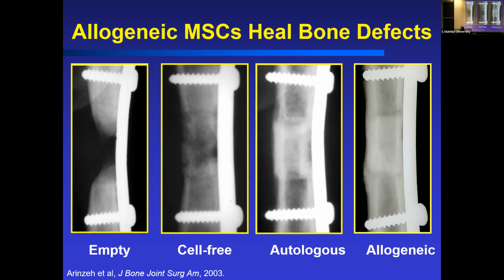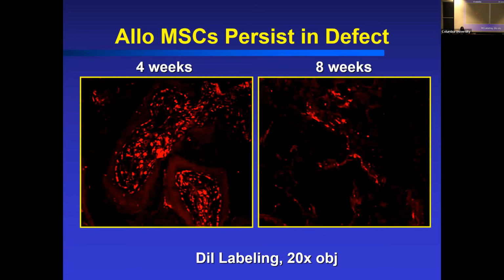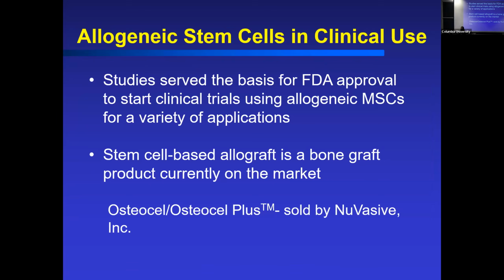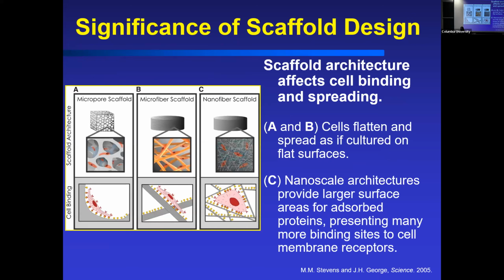So shown here are x-rays. Again, if you leave the bone untreated, you're left with this huge defect, right? Empty defect. But if you treat it with that combination of cells, you get this bridging of the defect. And so you follow that with a number of different outcomes of histology and we had to look for whether the cells were present. And so we were able to show that those cells were present in those tissues, building the bone tissue along with integrated with the scaffold over time. So this really served the basis then for FDA approval for the use of these donor cells for a number of clinical trials. Again, establishing that they're safe and efficacious in particular for bone, but there are other studies and for other applications. And there's currently a product on the market that utilizes this approach, this Osteocel Plus.